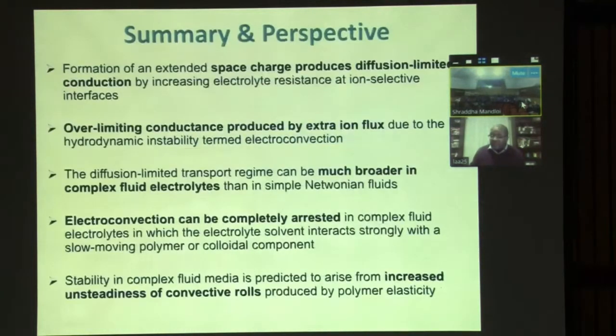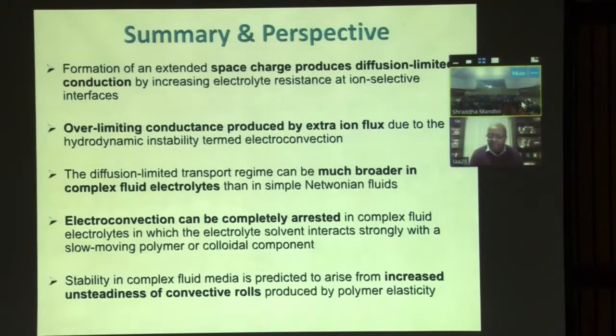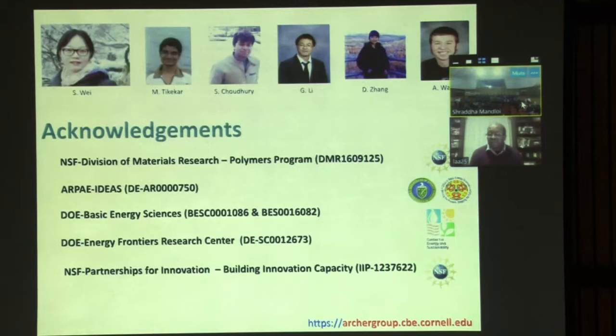The message I hope to have communicated is this: first, I would have loved to be there in person to get your questions. But we think there is a pretty important role for polymers in suppressing hydrodynamic instabilities as well as the morphological instabilities driven by them. We believe polymers extend the diffusion-limited regime. Most importantly, we believe they do it through an unusual process: in the bulk they appear to exert mostly viscous drag on the liquid without influencing the ions, while at the interface they create unsteadiness in the fluid flow that makes the flux at the interface more uniform.